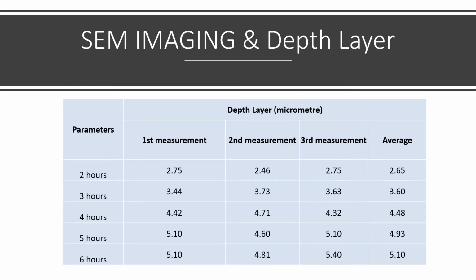Here are the tabulated data of the SEM imaging and the depth layer formation. For the 2 hours nitriding time, the average depth was measured at 2.6 micrometer, and it keeps increasing steadily up until 6 hours. For the 3 hours, the average depth was 3.6 micrometer, for 4 hours, the average was 4.4 micrometer, 5 hours was at the average of 4.93 micrometer, and for the 6 hours, which is the highest average depth, 5.10 micrometer.